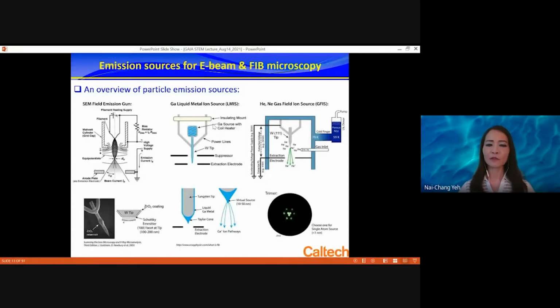And then for ion beams, you can use a gallium ion beam. The reason is that gallium has a very low melting temperature. So you heat it up, then gallium will become liquid, and then you use a negative voltage to extract the positive ions coming out. This is a zoomed-in picture: the liquid, heated to a low temperature, already forms a liquid, and the liquid can form a sharp tip. Then you can extract it by bias voltage, and the ions can come out.